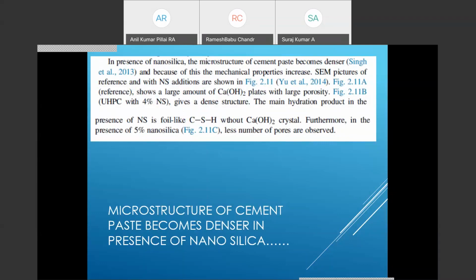The main hydration product in the presence of nanosilica is a foil-like calcium silicate hydrate gel without calcium hydroxide crystal. Furthermore, in presence of 5% of nanosilica, a lesser number of pores are observed. So on increasing the quantity of nanosilica, the pores get reduced. So the microstructure of the cement paste becomes denser in presence of nanosilica, is the result that has been produced by